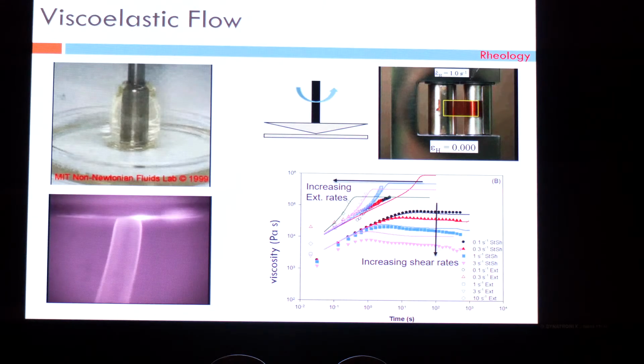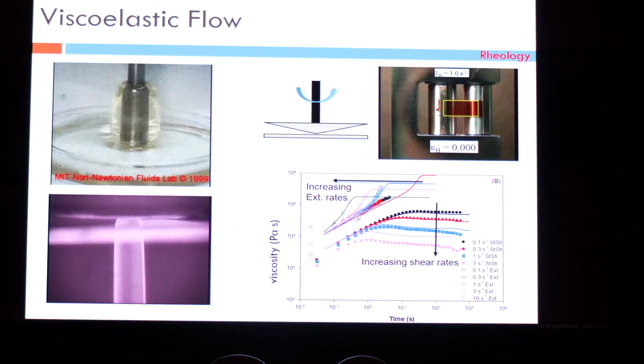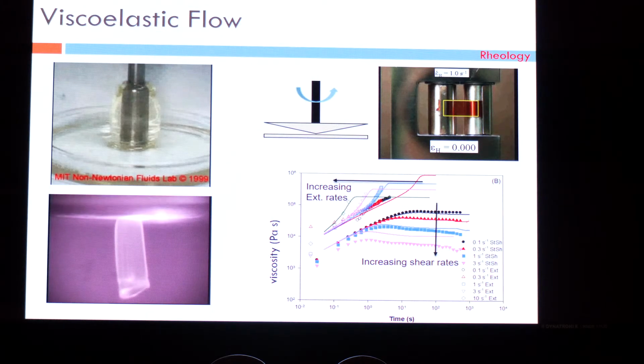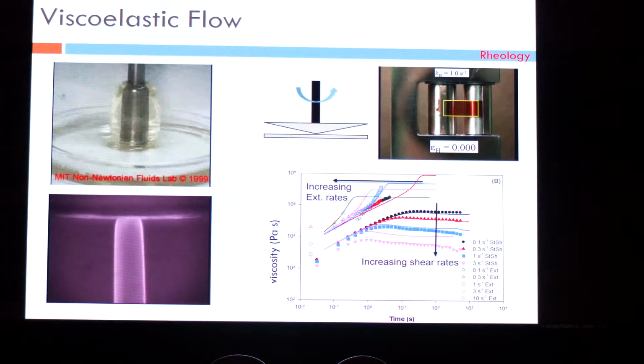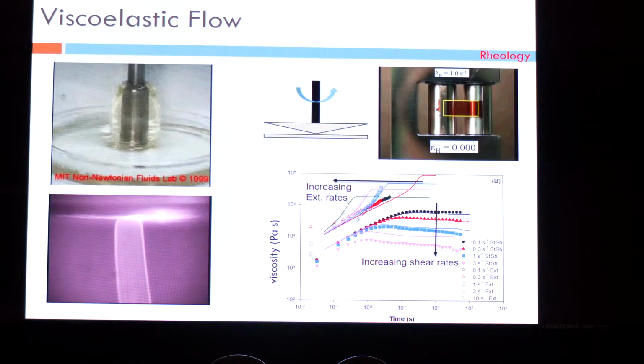In the bottom video that is playing, you will see a polymeric liquid that is extruding out of a die. And it's actually a liquid that is flowing, but you can cut it almost like a solid. And so it behaves like a liquid, it also behaves like a solid. When it extrudes out of that die, it actually swells. So the diameter of this polymer liquid is actually something like 150% more, 250% more than the die through which the polymer is being extruded out.